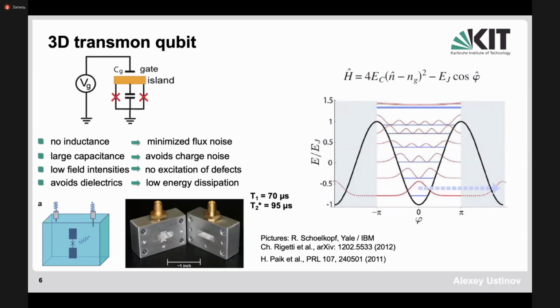So the loss in the resonator is small. That's one thing. But also in the qubit, it turns out that the losses in the qubit and the coherence times are predominantly determined by the loss in dielectrics on the surface of superconducting films. The physical mechanisms of this loss we are going to discuss next week when we discuss two-level systems, two-level defects in qubits.